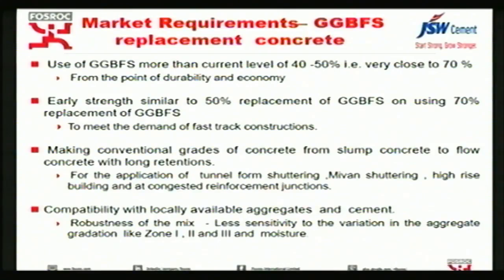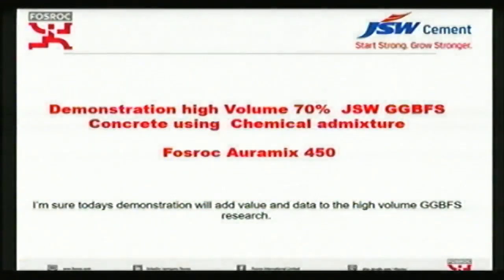Also, when we are using high volume slag or chemical admixtures, this should be robust enough and less sensitive to any variation in the sand grade, or when we are using such a high fly ash, the other aggregates also need to support. Just to give one example, the other day we were at Bangalore International Airport where they are doing the PQC. Even though they are getting the required strengths at around 50 to 60% replacement, because of the aggregate, the QC manager has said they are restricting it to around 40 to 50%. So the quality of aggregate is also very important. With 70% GGBFS from JSW and with our admixture Auramix 450, I'm sure this is going to add some data and value to these high volume requirements.